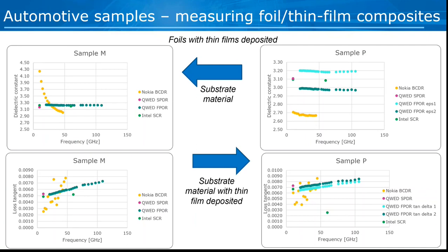The other really challenging samples included in the automotive kit were these thin film composites. On the left-hand side, we're showing the real part of permittivity, the dielectric constant, and the loss tangent of the blank substrate, showing that those are grouping pretty nicely.